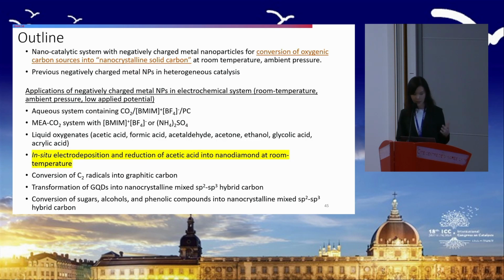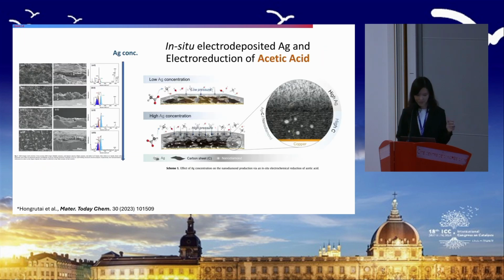So we learned that we can do in situ electrodeposition and reduction. In this work, we tried to vary the amount of silver that we put. It turned out that if we have too little, like on the top one, that's very little, maybe too little silver to make this happen. But if you start to have enough silver, you even end up having some nanodiamond here.